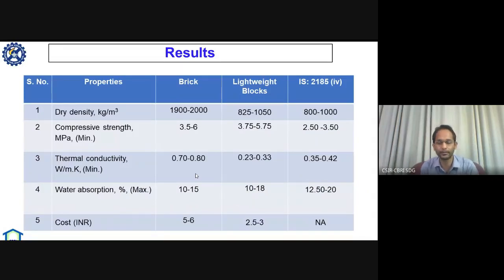Now I will tell you briefly what properties we have achieved as compared to brick, and what should be there as per IS 2185 part 4. The dry density, of course, was in the range of 825 to 1050. Our target range was 800 to 1000 kg per meter cube, so the error was very small. Our mix design was such that we achieved nearly the exact target density we wanted. And as you are aware, normally class 1, class 2, class 3 types of bricks have density of 1900 to 2000 kg per meter cube.